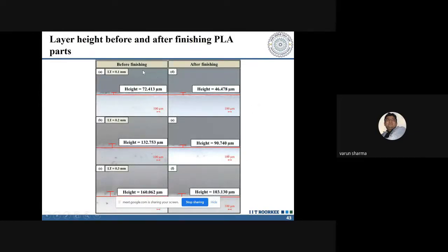Okay. I hope you would have heard up until this particular point. So what I was discussing over here is that for layer thickness of 0.1 mm, we were able to reduce the height from 72 microns to 46 microns. For 0.2 layer thickness, this height was reduced from 132 to 90 microns. And for 0.3, this height was reduced from 160 to 103 microns.